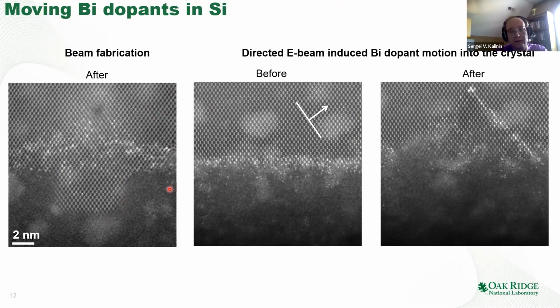But what we learned at that time is that not only can we crystallize silicon, but somehow we can also make these white marker atoms move around. You can see that some of them moved. In this case, if we scan the electron beam, you can see that we have created a front of these dopants inside the three-dimensional material. Now we are talking about something really unusual. In this case, we are not controlling the atom on the surface. We are controlling the atom inside the bulk. Very thin bulk, 50 nanometers, but still bulk.